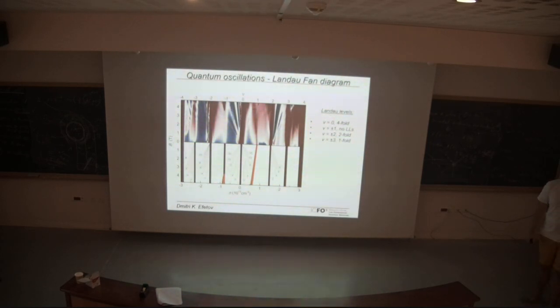I'm a little puzzled by those data from the following point of view. Here the moire lattice space is 14 nanometers. Right. So for example, at 4 Tesla, you have a magnetic length that is roughly the same, even smaller, than the lattice space. So you should be rather in a Hofstadter butterfly. Right. Yeah.